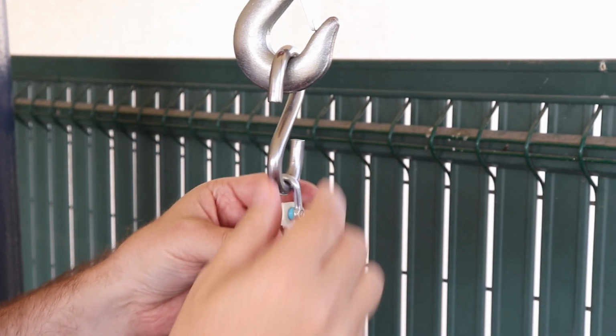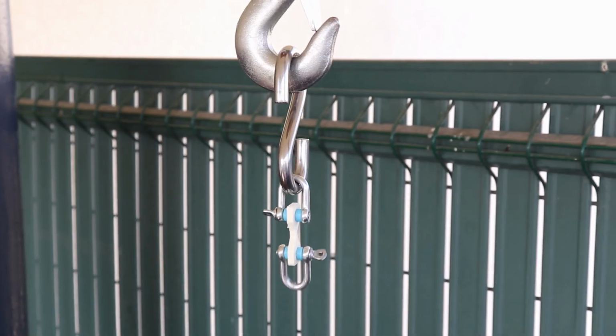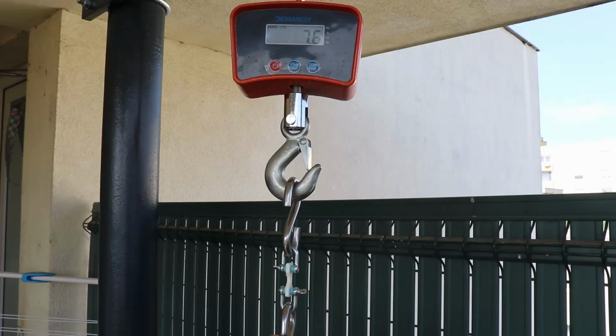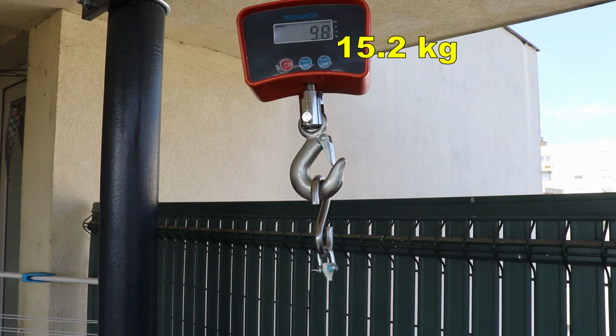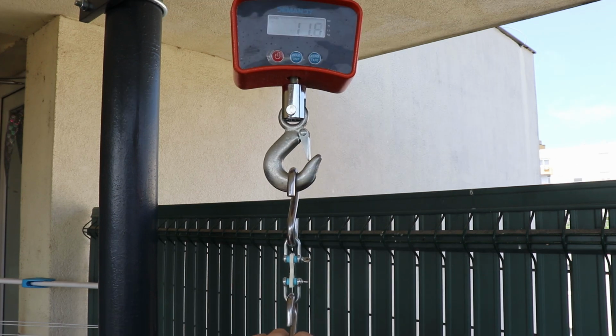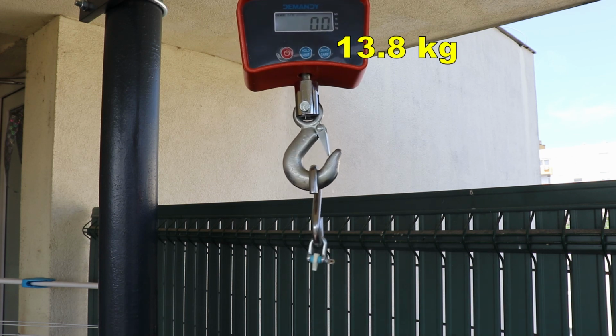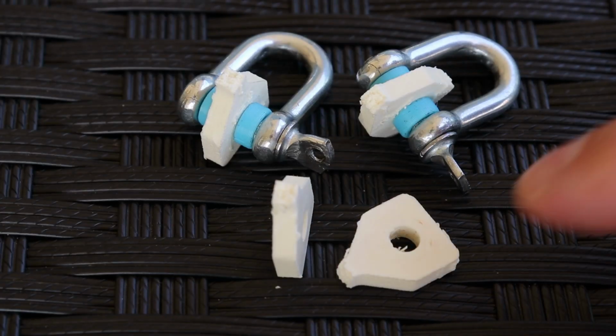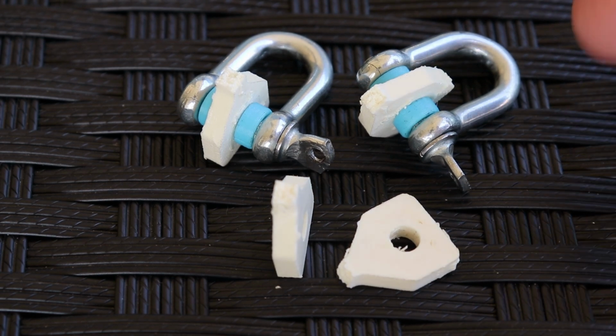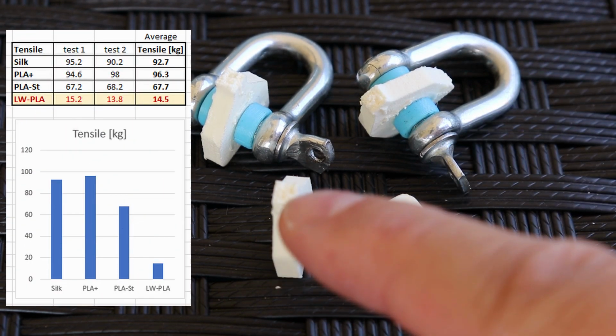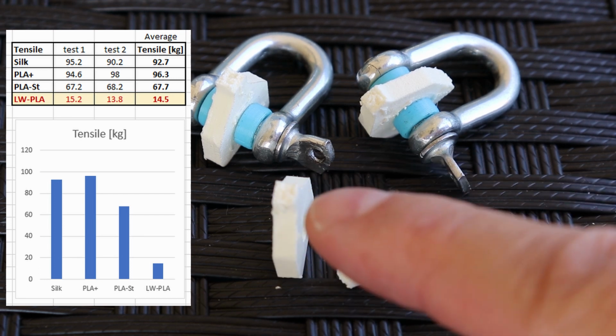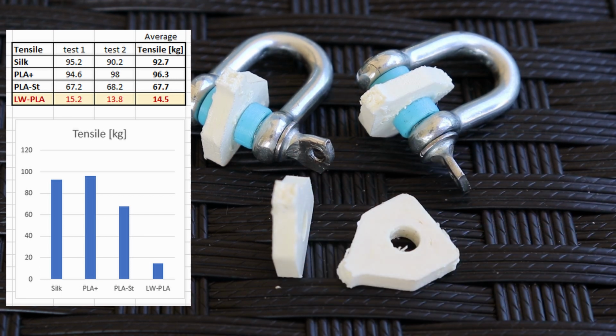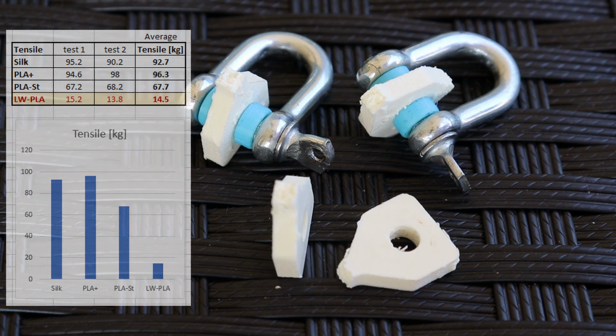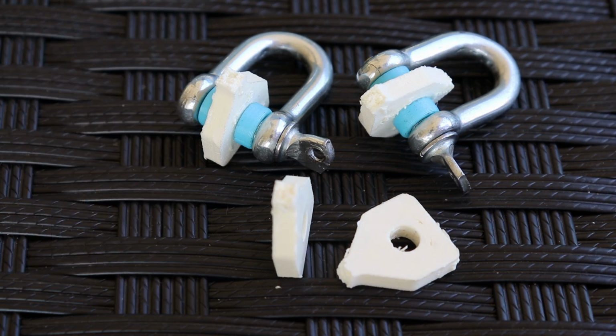And now the tensile strength test, and these test specimens are printed in horizontal position. And again, these are my standard test specimens. The smallest cross-section area is 4 by 4 millimeters. So these results are also comparable with other experiments. Well, again, from the first feeling, definitely this is not as strong as a regular PLA in tensile strength, but actually I can see the air, the foam in this cross-section. So it is normal that this has to be weaker because the real cross-section is not 4 by 4 millimeters, but it is reduced because there are air gaps in the material.